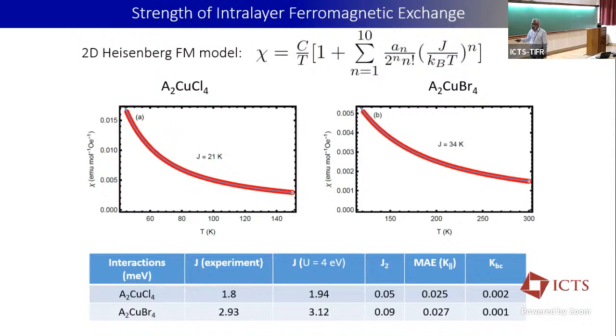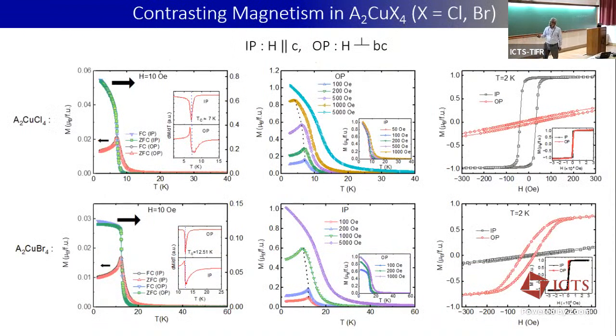So this is from our experiment. If you convert it to milli-electron volts, it comes to 1.8 meV for the chlorine, and this is roughly 2.93. And we wanted to check with the theoretical calculation, which was done by our collaborators. So this also comes to 1.94 and 3.12. And if you calculate the J2, the next nearest neighbor interaction, that was coming out ferromagnetic. In both cases, we calculated that the anisotropy remains in the plane. So if the anisotropy remains in the plane in both cases, both these systems should show a similar kind of behavior, but that is not the case.